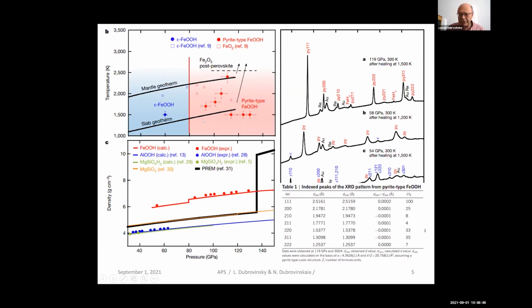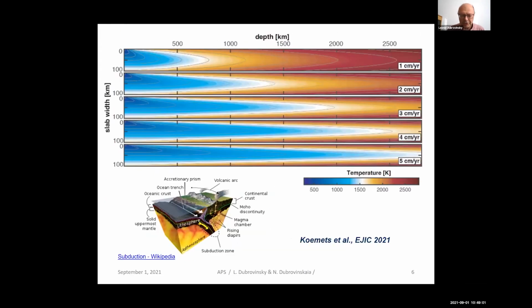I don't think this approach is really correct. We need to first estimate which temperature and pressure we should achieve in our experiments to model the process. And we used, I would say, a semi-quantitative approach. We considered the slab one-dimensional, very simple, with a thickness of 100 kilometers. We looked at the speed with which the slab is going deep into the mantle. In fact, we are interested only in the vertical component of the speed.